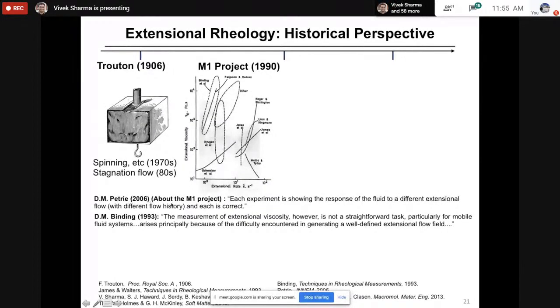And around 2006, it was realized that each experiment is showing the response of the fluid to a different extensional flow with different flow history, and each is correct. That does not really help us much, but it tells you that it's important to know what is the right measurement, and it's also important to control the deformation history. As it turns out, most of these fluids are very high viscosity fluids. M1 fluid was a very high viscosity fluid. When we think about sprayable paints or inks or sprayable insecticides and pesticides, the actual viscosity values are rather low and the extension rates are rather high, and most of these techniques cannot be used for those.